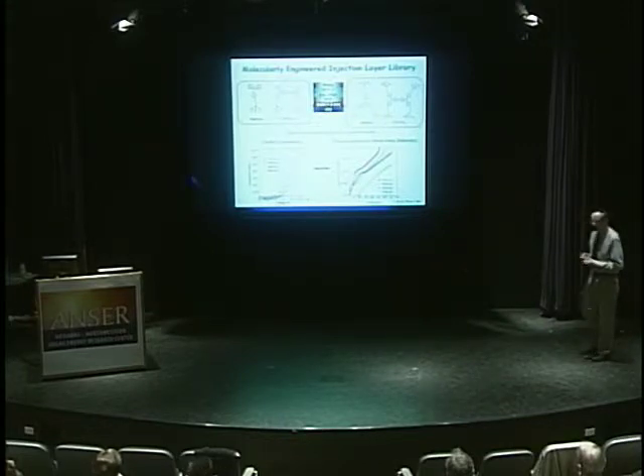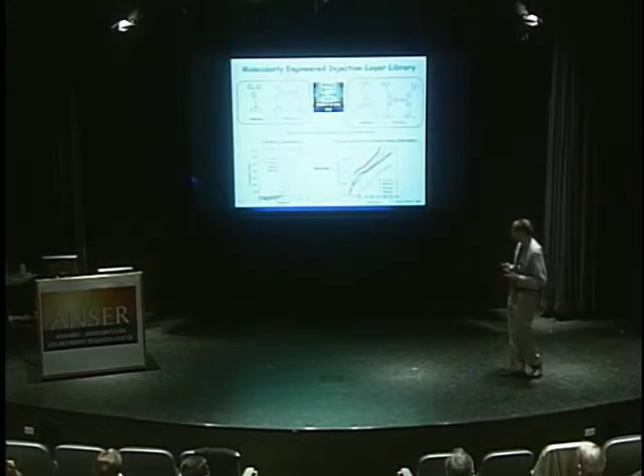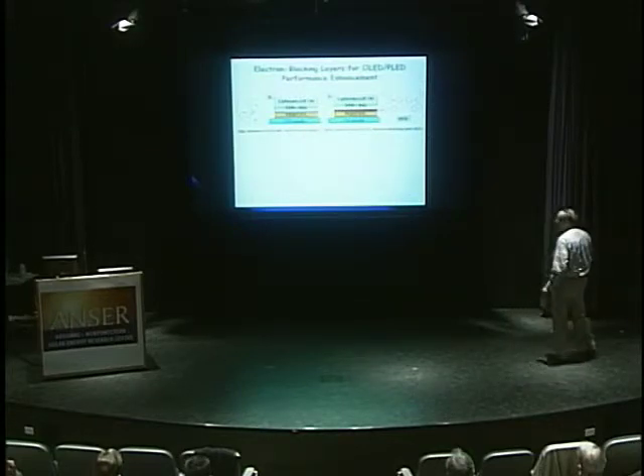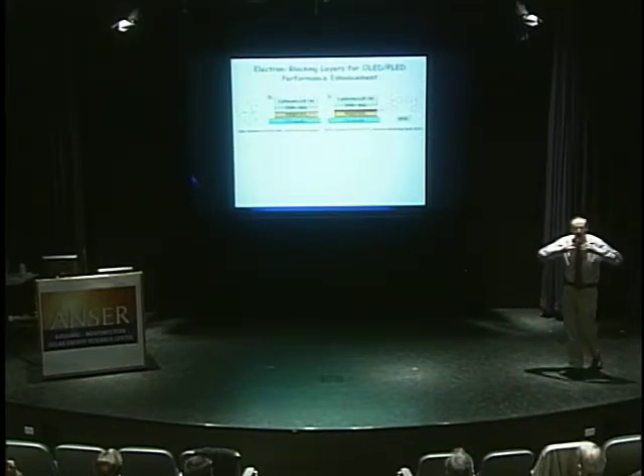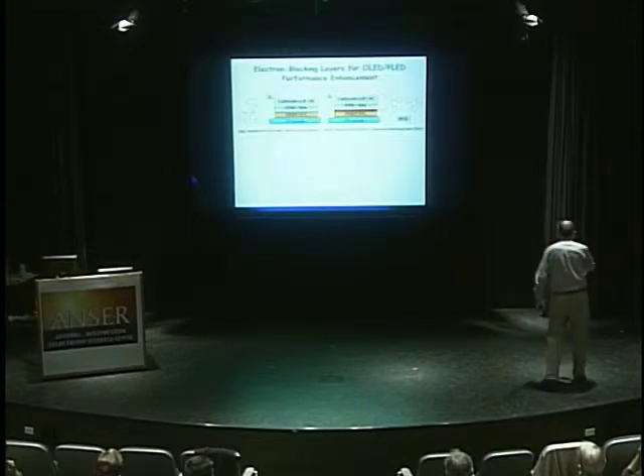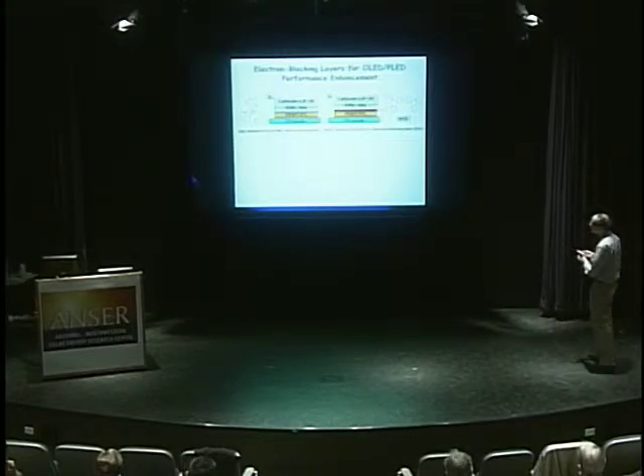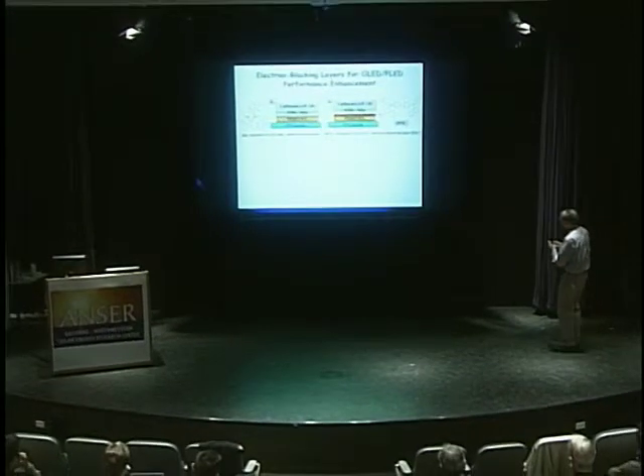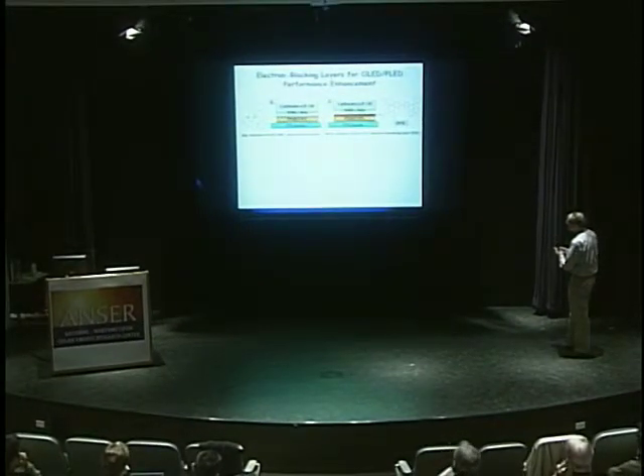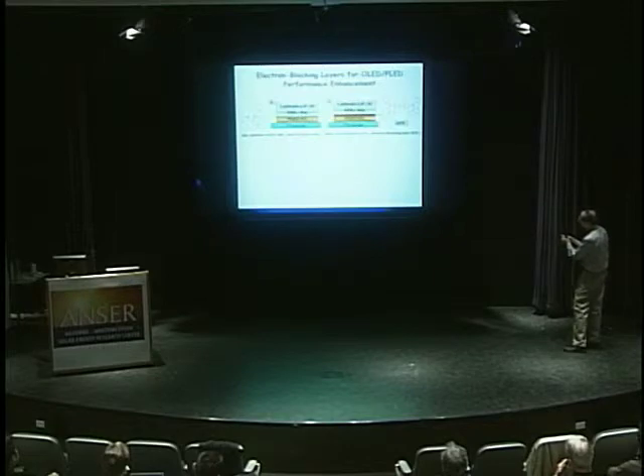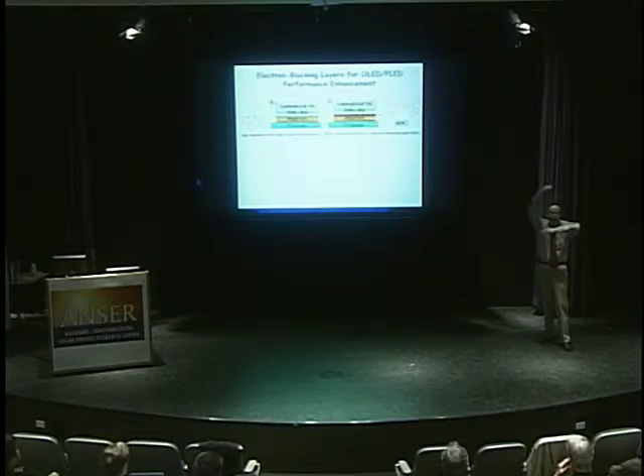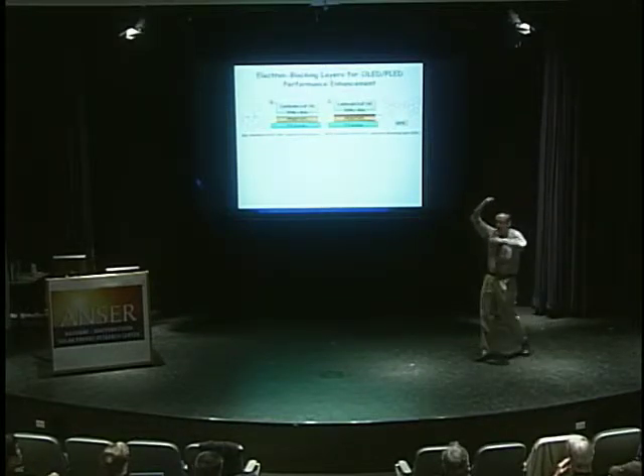So the intriguing thing here is there are suggestions for how you might modify the OPV structure for just the same purposes. This is Henry Yan's work, and this takes it one step further. These are some polymer light-emitting diodes, and what Henry compared was the performance of one that's got a cathode, an emissive layer, PEDOT, and ITO with the same structure, where he vapor deposited just a few nanometers of this material, because this material has a very high lying LUMO. It's been used as an electron blocker.